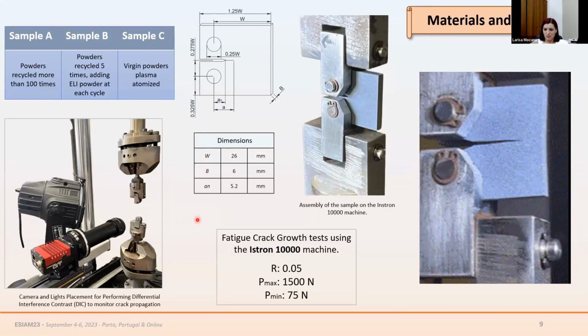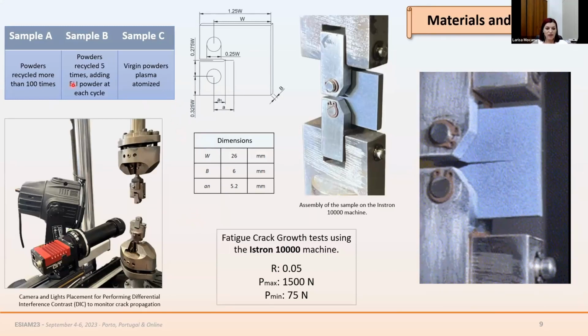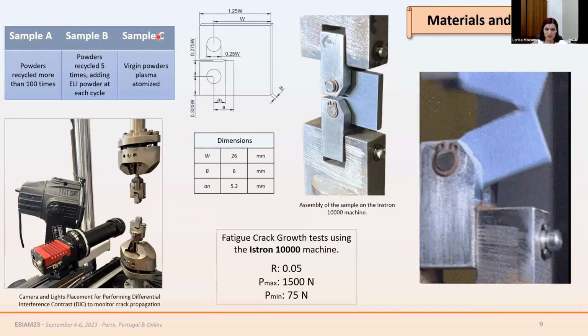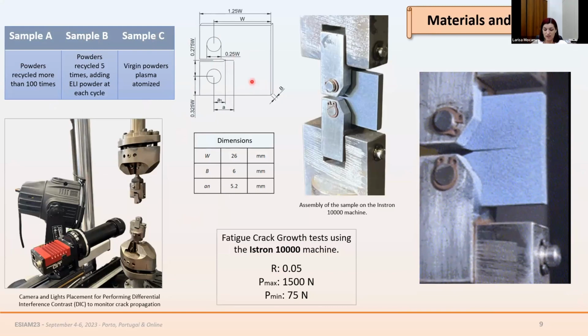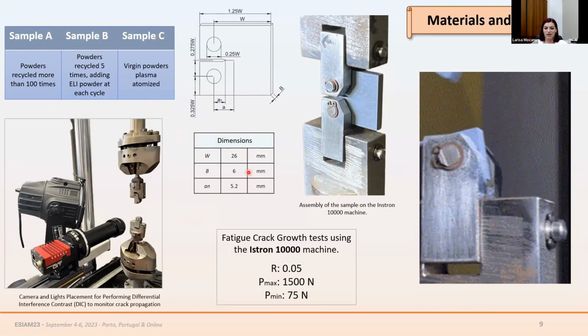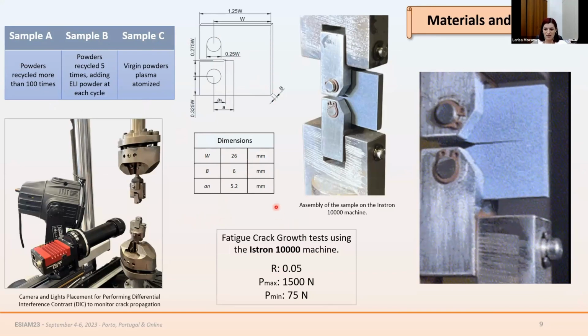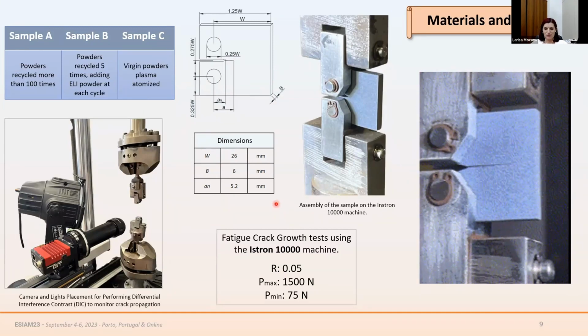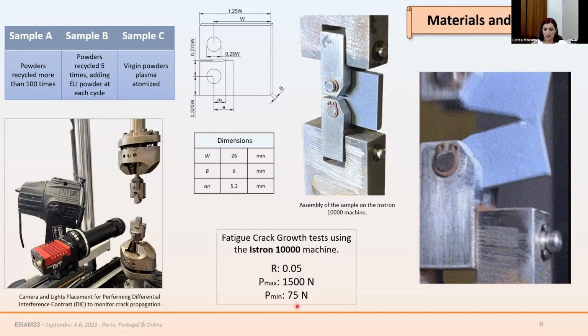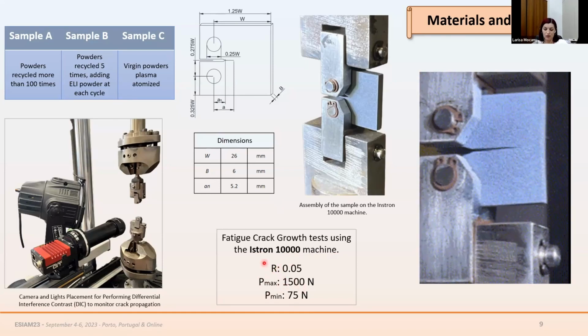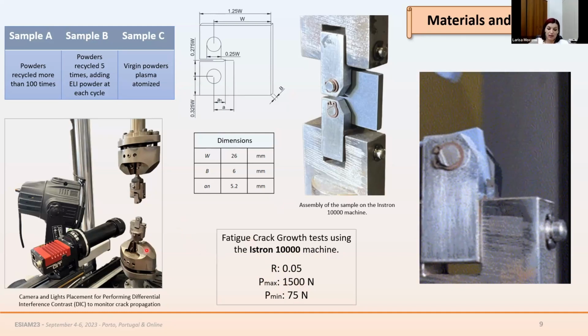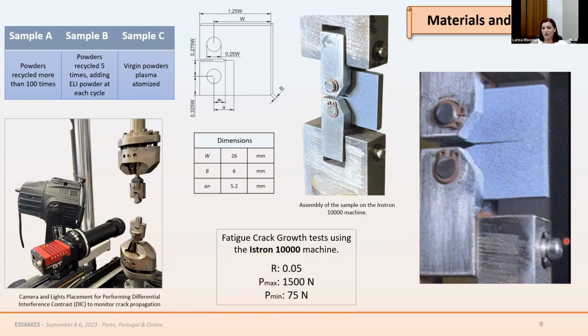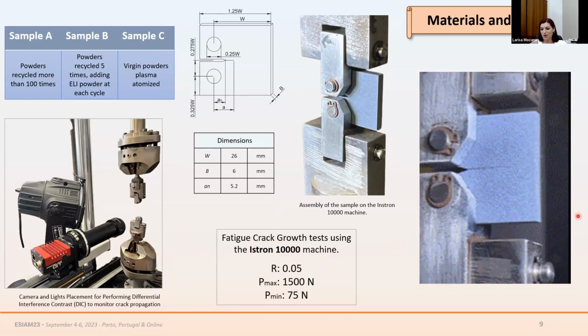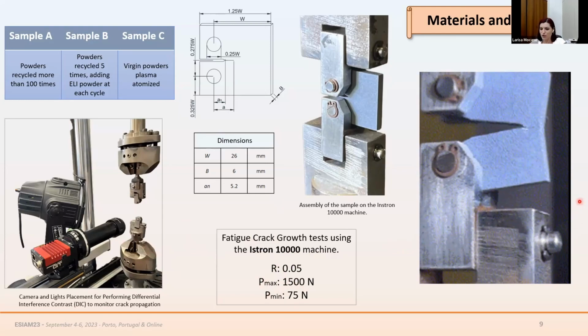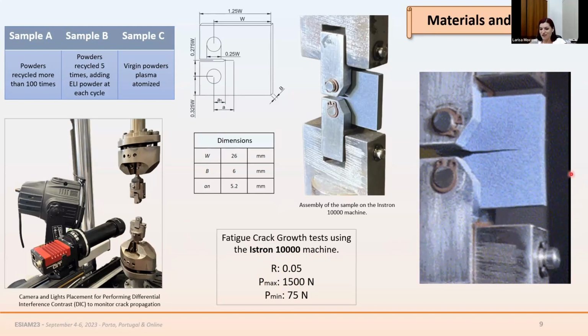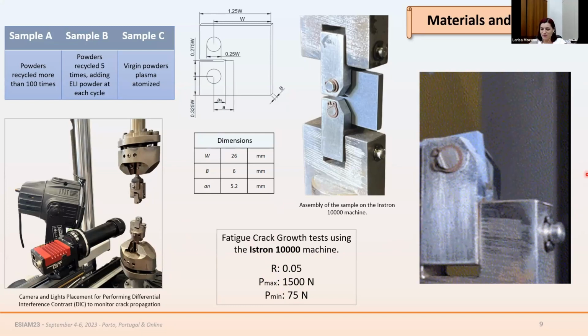Regarding the crack growth propagation behavior in this presentation, we investigated three kinds of samples: sample A, sample B, and sample C. Here is displayed the CT sample, and here are the dimensions. Then we performed this fatigue crack propagation test using this Instron 10000 machine, and here are displayed the characteristics of the test. And then we monitored the crack length using DIC. Here on the right, we can also see an interesting moment when the sample reaches the final fracture. Of course, this is not the real speed of the test. I just wanted to highlight this moment.